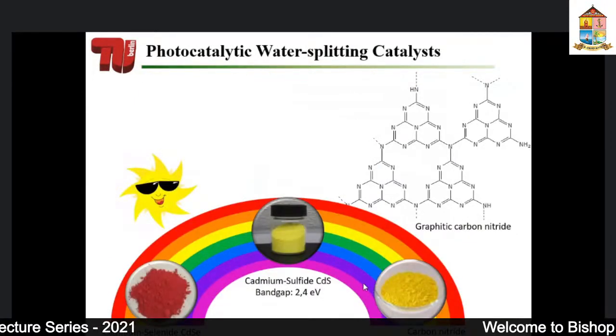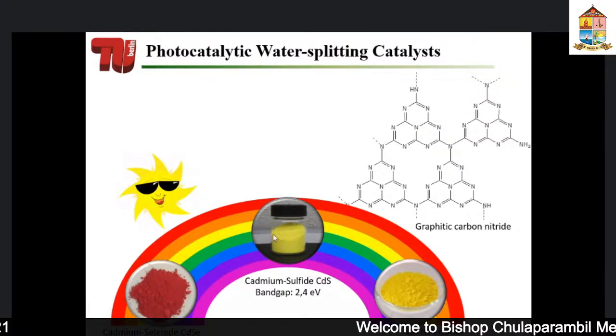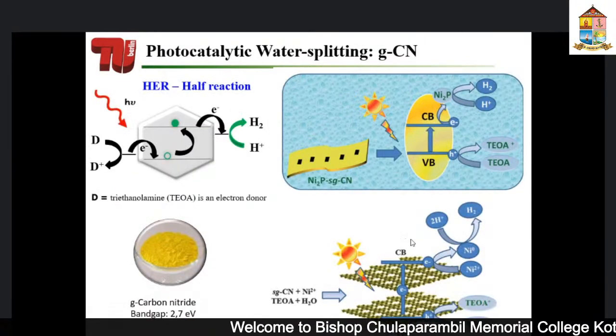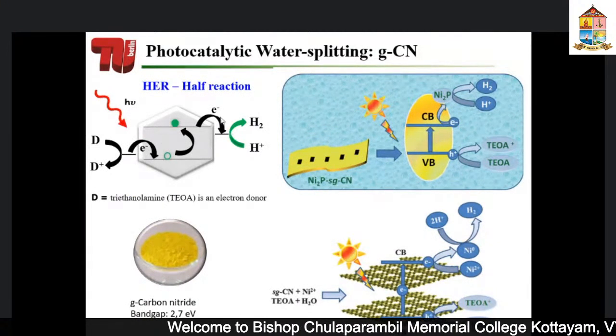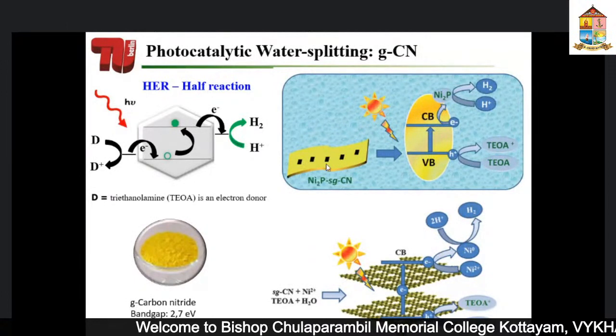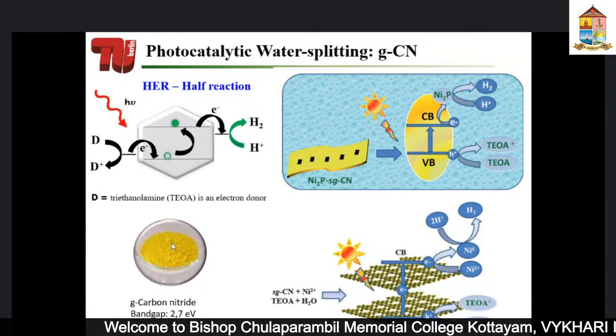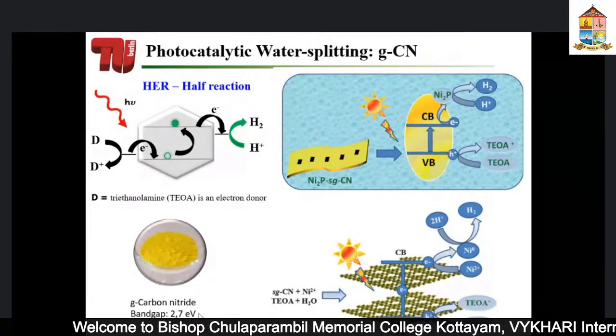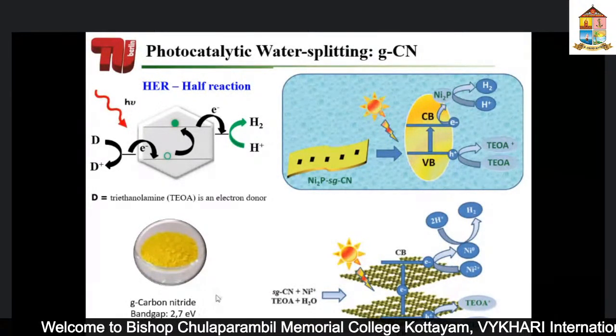There are some catalysts which are already prominent in this area. For example, cadmium selenide, which has a band gap of 1.7, which is very suitable for the hydrogen evolution reaction. Also cadmium sulfide and carbon nitride, which is a metal-free catalyst and very popular nowadays. Nevertheless, what I want to show is that we also worked on some of these reactions where, as I said, we quench the hole and produce only hydrogen. This is the carbon nitride as shown here, which is yellow in color. The band gap of this material is almost 2.7 volts.